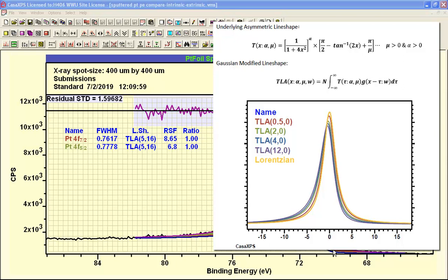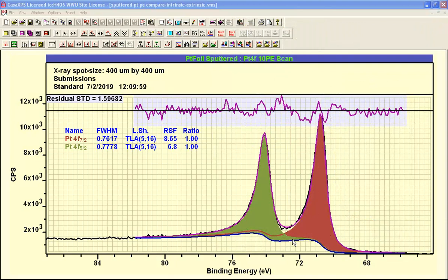In this video, we're going to look at asymmetry in photoemission peaks. The source for asymmetry is multifactorial, and one of the more significant factors in the shape of these photoemission peaks is the shape of the inelastically scattered background that is associated with the photoemission process. This blue line represents the inelastically scattered background that has to be subtracted from the photoemission peaks so that we're left with what should be the photoemission signal that has undergone no scattering as a result of electrons moving through the sample.